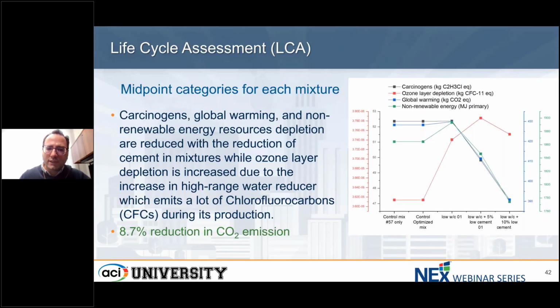These are results from the life cycle assessment. So you see, when we move from the control mix to the sustainable mix, which is low water cement, 10% low cement, except for the ozone layer depletion, the other 3 criteria or midpoint categories, we see reduction, right? Which is a good thing. But regarding the ozone layer depletion, we see an increase when we move from control to the low water cement ratio system. And the big driver for this is emission of CFCs from the high range water reducer, because we are increasing the dosage, so that contributes more to CFCs, and that's why you are seeing an increase here.